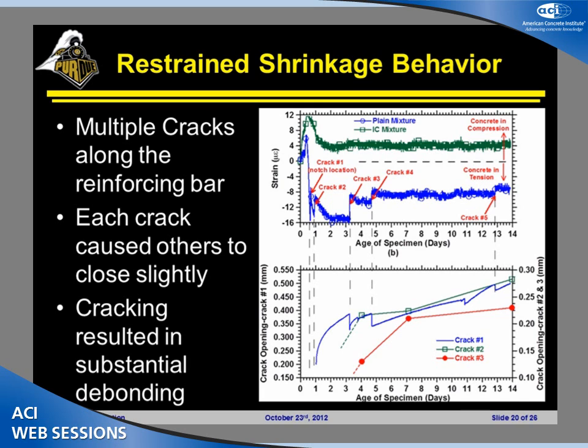Right after, I believe it was after about 2 weeks, we started to dry these elements out. The blue one, though, you can see there are several of these jumps in the data. You may say, oh, there must be something funny happening in the data. Well, those jumps are something funny that's happening. Those jumps are cracks. And what's interesting about this is the gauge section is about 8 feet long, and we picked up at least 3 cracks that formed in that 8-foot section. So about every 3 feet, we're getting cracking in the system.